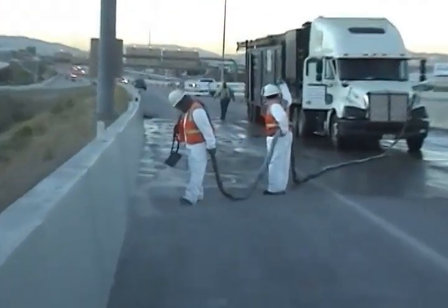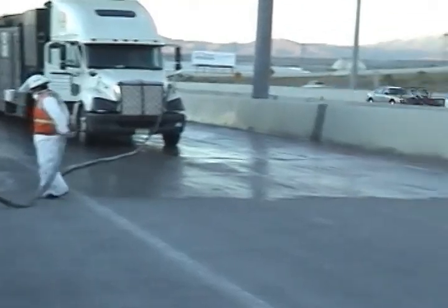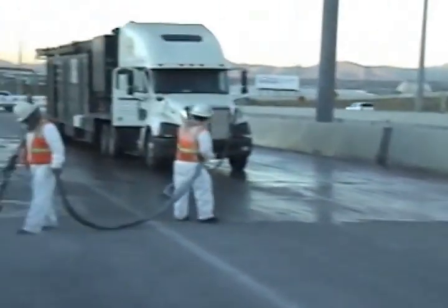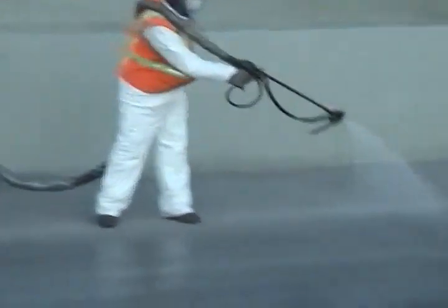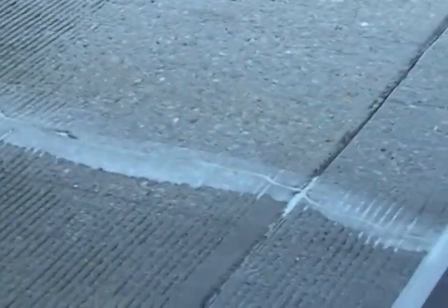The final stage of deck preparation entails the application of a low viscosity methacrylate. This material is intended to penetrate and seal the small cracks that have formed in the concrete in the years since its construction. Once the cracks have been sealed, the deck is ready to receive the FlexoGrid overlay.